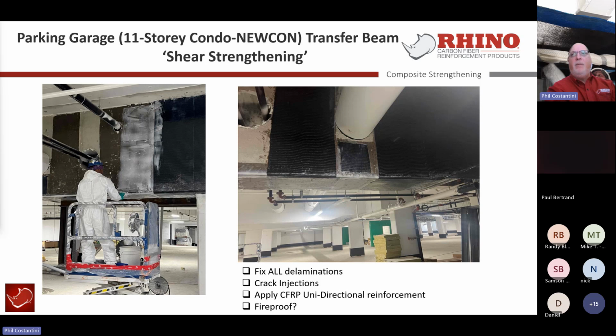There were cracks in the beam over by the columns that were supporting it on either side. Those had to be injected. And then eventually we had to apply our CFRP 710 GSM unidirectional reinforcement material in both a unidirectional and shear reinforcing on the underside on the entire beam. So this isn't your typical axial reinforcing where we're just going to do it around the openings. No, this beam had to basically be completely reinforced from end to end. And that's exactly what happened in this application in order to get it strengthened enough to carry on.